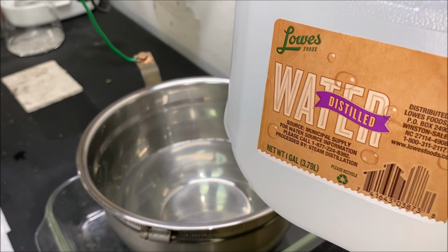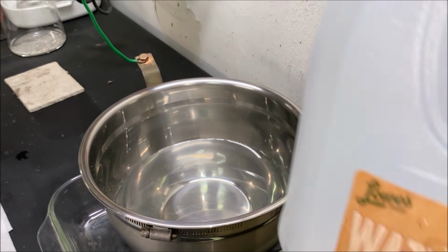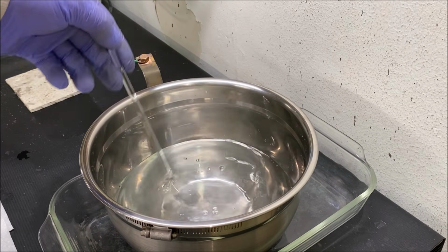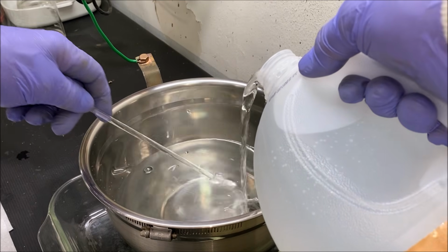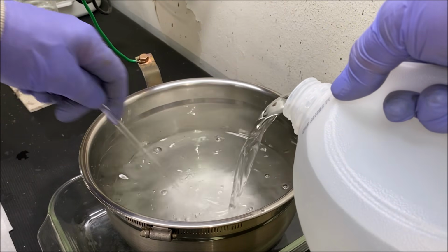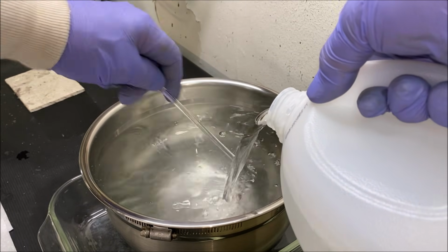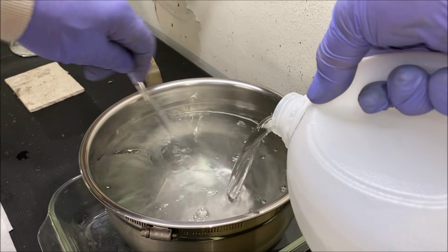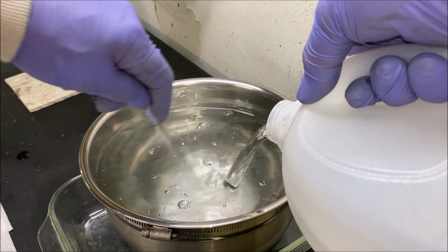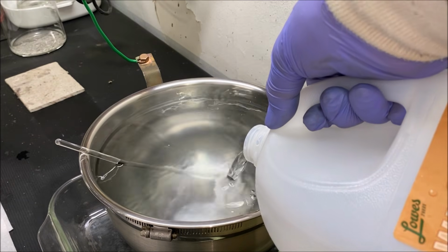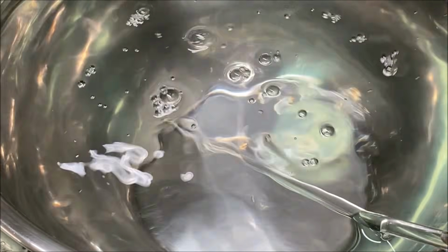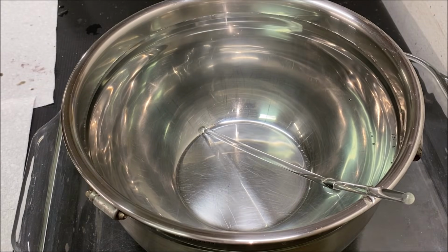Now what we'll do is add some distilled water. There is about 600 grams of pure silver in here, dissolved in this solution. We're going to top it up to within a half an inch of the rim of the silver cell now with distilled water. Stir it up real good to make sure we've got a nice homogeneous solution. Now we'll put the cover on.